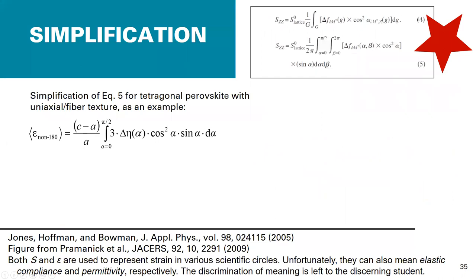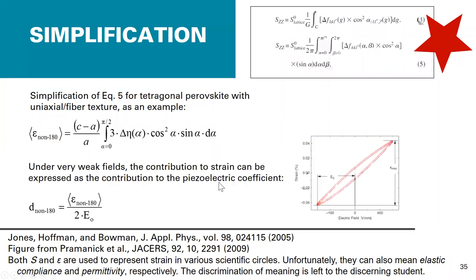And we've represented it using a single integral over alpha, because in most cases, not all, but most, we have a uniaxial pole figure, or in other words, a fiber texture. Okay, so we're not interested in beta. And so the strain resulting from switching can be described according to this equation. Under very weak fields, the contribution to strain can be expressed as the contribution to the piezoelectric coefficient. And so here's a third connection point, right? First, we calculated the degree of switching. Then we calculated how that influenced macroscopic strain. And if we do it at weak fields, we could determine the contribution to the piezo coefficient from that mechanism.